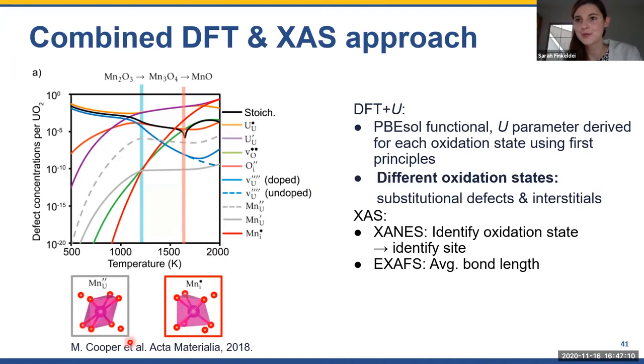So we are trying to bring experimental proof for manganese, which is supposed to be a superior dopant to chrome, as it's supposed to enable the growth of even larger grains than chromium-doped UO2. But a similar phenomenon is observed with chromium too. Do we understand why chromium is acting to increase the grain size? They describe in their paper that the way chromium is accessing the uranium dioxide is that at a certain temperature, the solution mechanism changes, and you're increasing the vacancies of uranium, and therefore you're increasing the diffusion and thus allowing for the growth of larger grains.